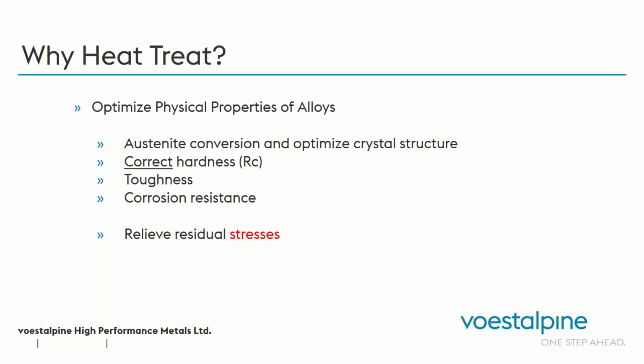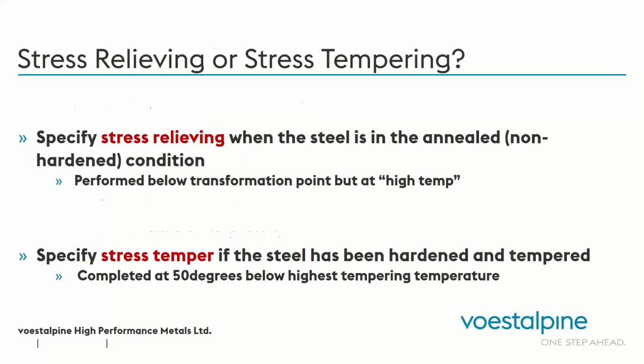And that's important because based on current geometries, complex geometries or size of blocks, the last thing you want is residual stresses in the material that can result in cracking and distortion and so forth. Now, there's two types of stresses or stress relieving that we can consider. And we get a little more specific than some heat treaters, although other heat treaters do use this nomenclature, but we have stress relieving and stress temper. So these are both processes that reduce or de-stress your tooling.